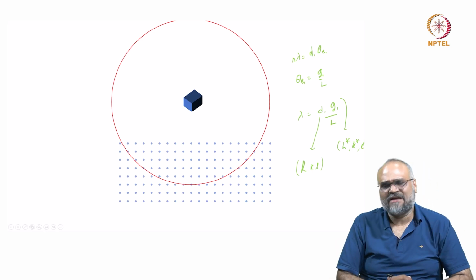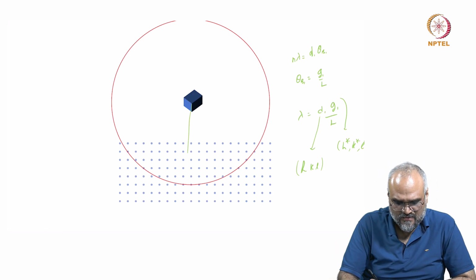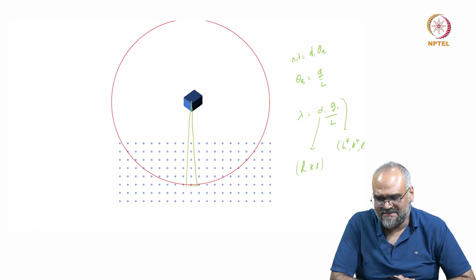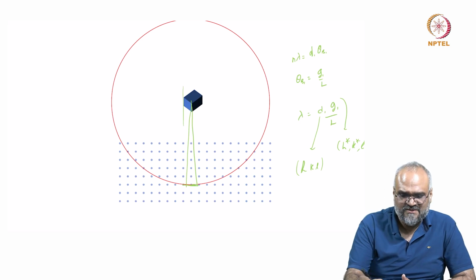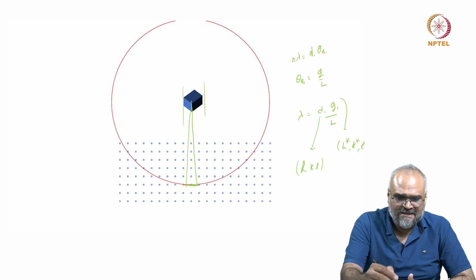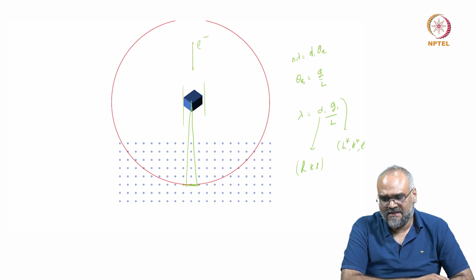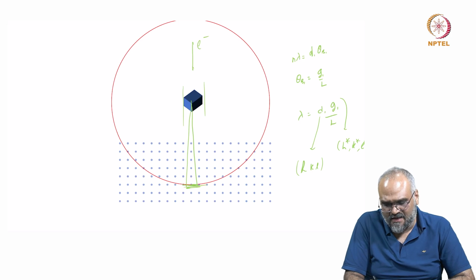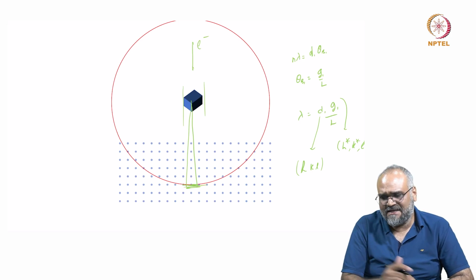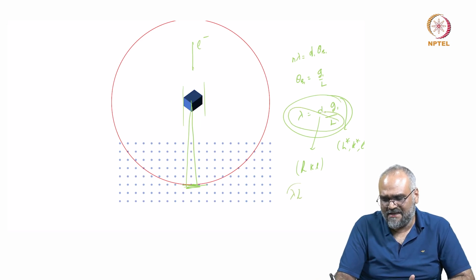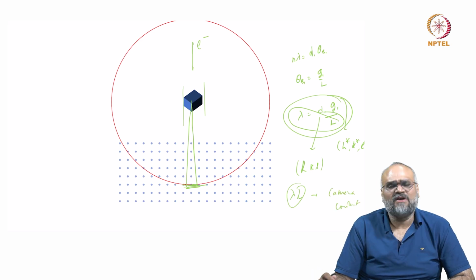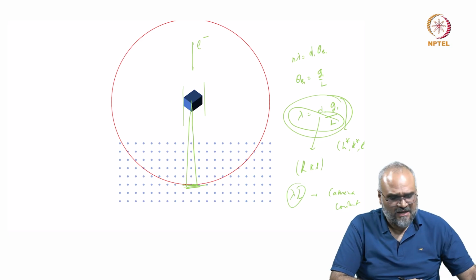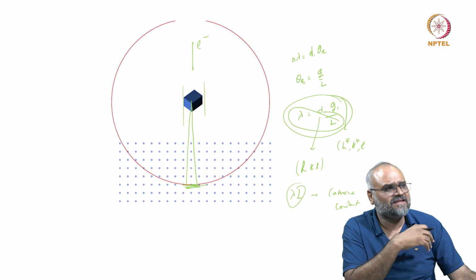And in an electron microscope, I can link these distances through a simple geometric relation, and let us say if these two are the first order reflections from these planes which are satisfying Bragg's law, and this is again parallel to the electron beam, the projections whatever I record in an electron microscope can simply be linked through this kind of a relation, and this value lambda L becomes a constant, and we call this a camera constant for electron diffraction patterns.